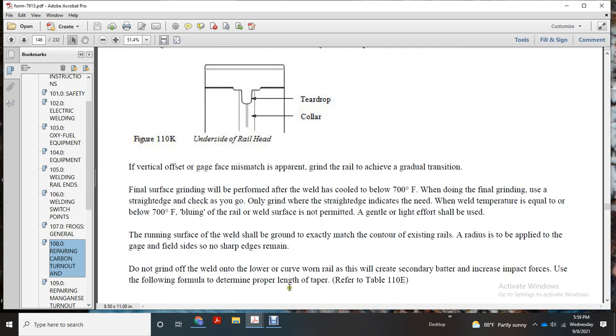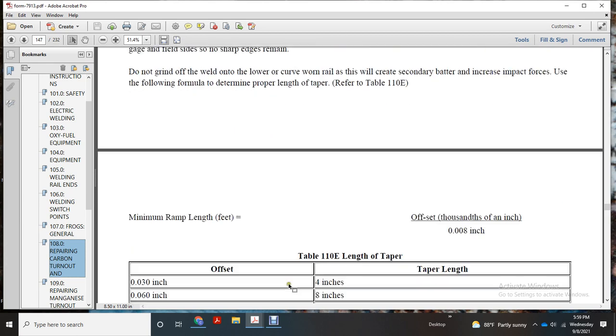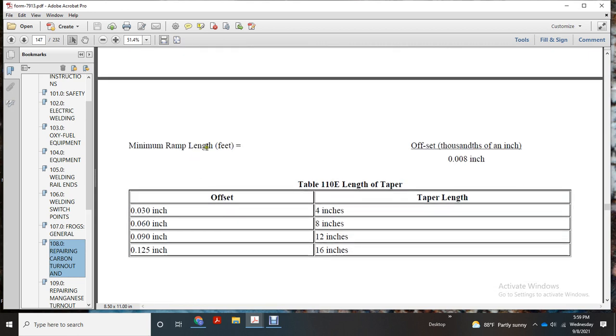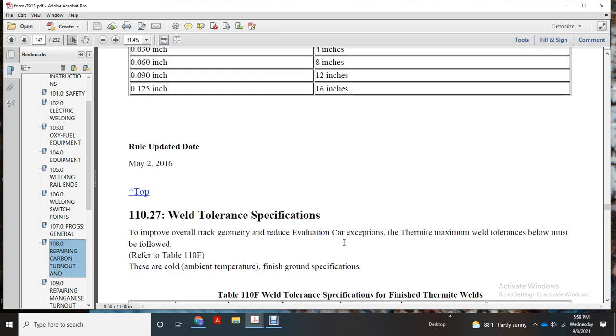Use the following formula to determine the proper ramp length with the taper, per table 110E. Minimum ramp length in feet is equal to the offset in thousandths of an inch over 8 thousandths of an inch. 30 thousandths of an inch: 4 inch taper length. 60 thousandths of an inch: 8 inch taper length. 90 thousandths of an inch: 12 inch taper length. 125 thousandths of an inch: 16 inch taper length. Weld tolerance and specification improve the overall track geometry and reduce evaluation car exceptions.